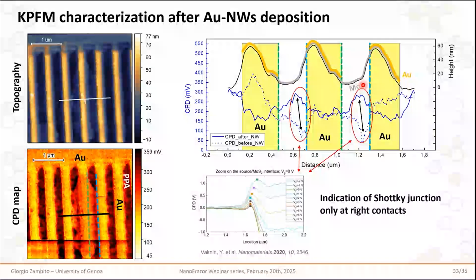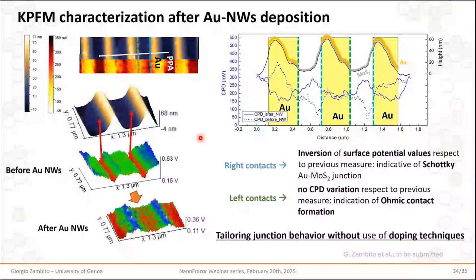On the contrary, we see a critical increase of CPD if we compare the CPD before and after nanowire deposition on right contacts. And this, if we compare with other results dealing with Kelvin probe force microscopy on MoS2 gold transistors, is an indication of the presence of a built-in electric field and hence of a Schottky junction. So the point is that we have an alternation of behavior. With this single nanowire deposition, we have an alternation of right and left contacts, and of Schottky and ohmic junctions. Usually, when working with semiconducting materials, you achieve this kind of control when you can use substitutional doping techniques in silicon manufacturing.